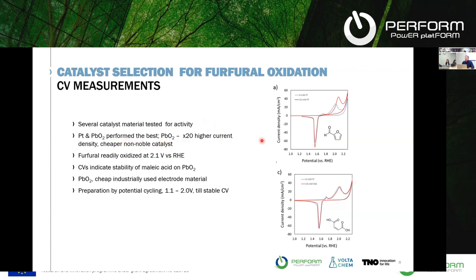This can be done on a very, very small scale, typically a few milliliters with an electrode. And you get graphs that look like that, and you look at the difference between when you have furfural in solution and when you don't have furfural in solution. So in the case of the red curve, you see that around 2 volts potential, you have an increase in current, and that's your furfural oxidation.